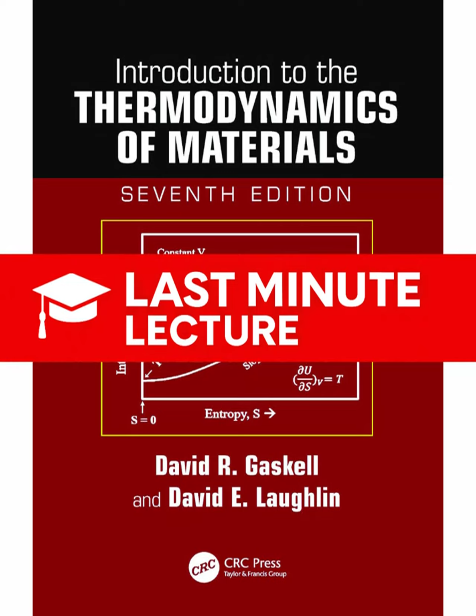Okay, let's go back to that crucial caveat. Complete internal equilibrium. We know real materials violate this all the time. Where do we see this so-called residual entropy? Oh, everywhere. Anywhere disorder gets frozen in, glasses are the classic example. They have the non-zero entropy of the liquid structure because the atoms just didn't have time to arrange into a perfect crystal on cooling. In solid solutions, too. Absolutely. Non-equilibrium solid solutions, where atoms are just randomly mixed on lattice sites, they retain that entropy of mixing.